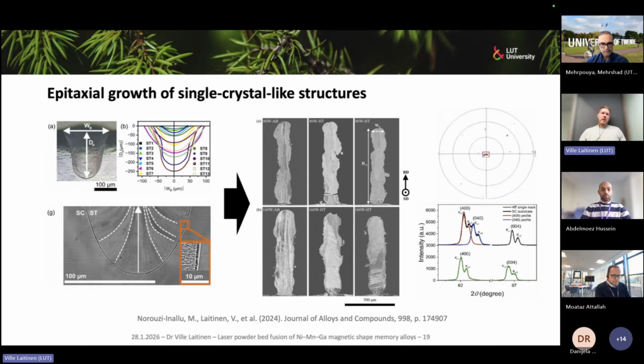In this case, we made something that is more of a thin wall structure, but we tailored the processing parameters in a way that the single track melting pool that we generate has a very sloped behavior, meaning that it's not very deep, but it's very wide. This forces the single crystal, or this crystallite, to grow in a very defined direction of the thermal gradient. This way we can make these wall structures where we have a crystal Z-axis pointing up during the process. Then in a post-processing heat treatment, those very similarly oriented grains can fuse together, and we can have something that is very close to single crystal.